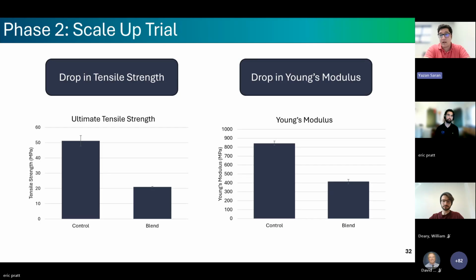We also performed tensile testing on our optimal blend, and we did find a significant drop in both tensile strength and the elastic modulus from our control polypropylene samples. This test, while not integral to the success of this application, still provided good information for us and actually tied very well into our reprocessability study, which Eric will now go into detail on.